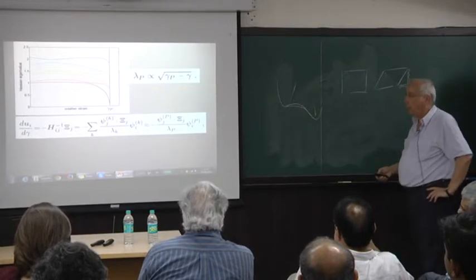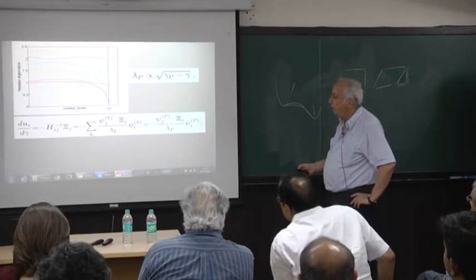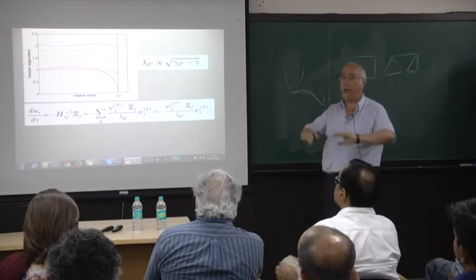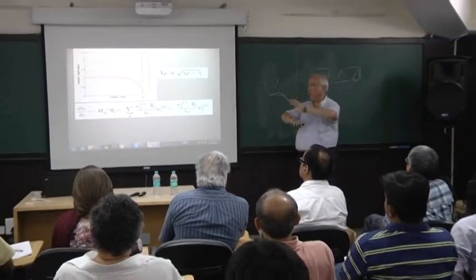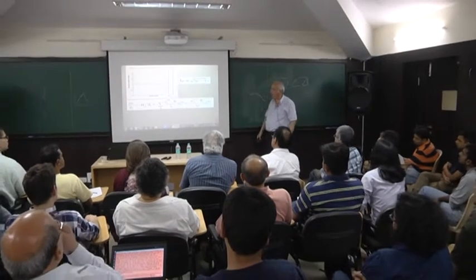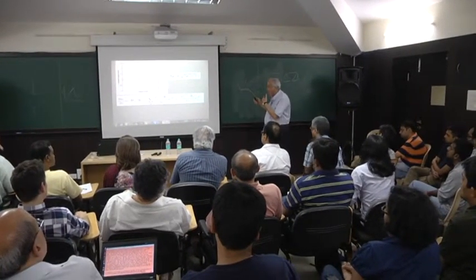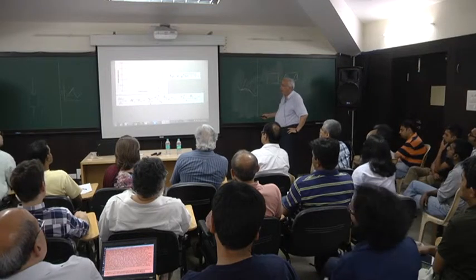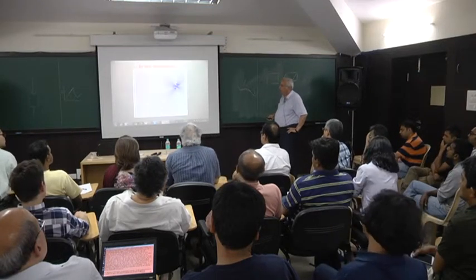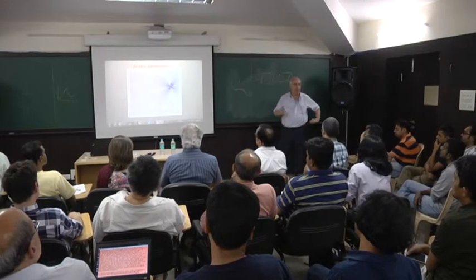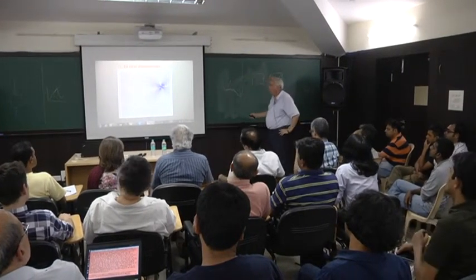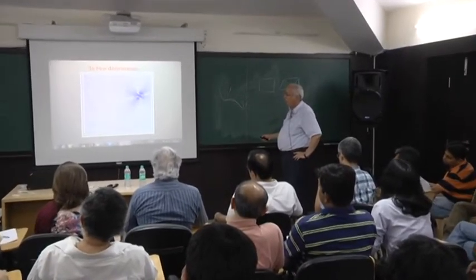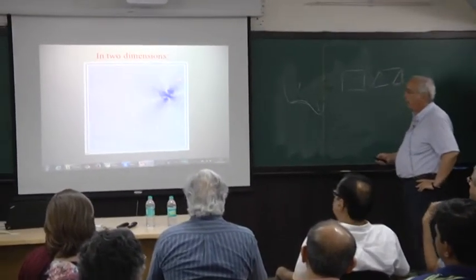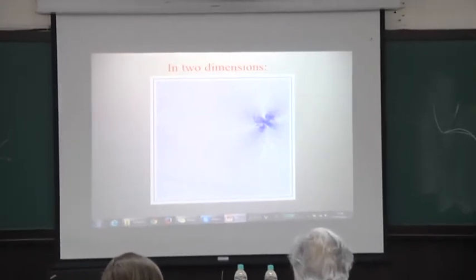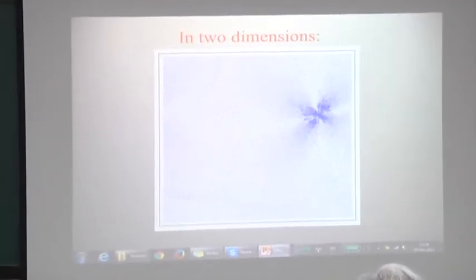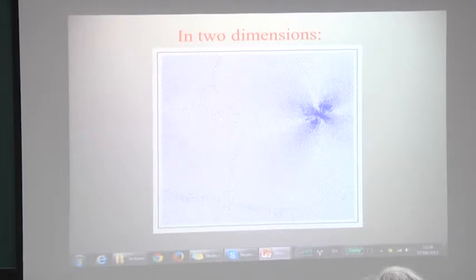So let's look at them. How do they look? Well, it turns out that when you're here at zero strain, all the eigenfunctions are delocalized. So the eigenfunctions are all over the space. There's nothing really that characterizes them as interesting. When you go down, when lambda begins to go to zero, there is a fantastic phenomenon of localization. And the eigenfunction that was delocalized there localizes on a structure like this that we've seen today already a couple of times. This is the famous quadrupole that I'm going to associate soon with an Eshelby phenomenon. But it's really a very simple thing.